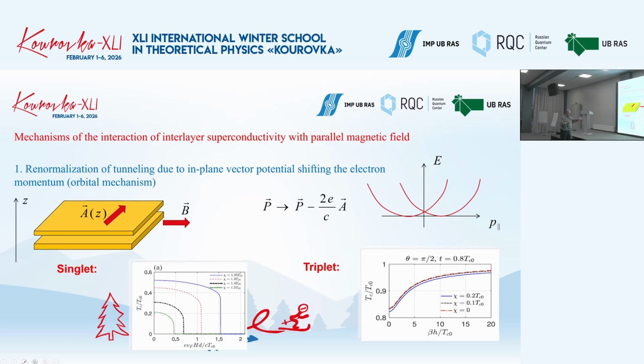And this is indeed the case, and we can again do these calculations both for singlet and triplet pairs. And we observed that in fact this mechanism results in suppression of tunneling. For instance, for triplet pairs, the critical temperature starts to increase as soon as we increase the magnetic field. But well, this is not the suppression. This is not the critical magnetic field. We cannot get a critical magnetic field in such a way. So we need something more beyond the orbital mechanism.